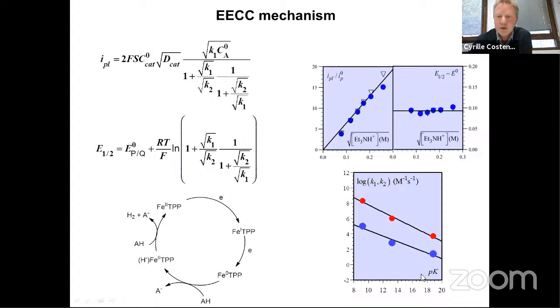And interestingly, if you change the pKa of the substrate, the acid molecule, you get a correlation between the rate constant and the pKa of the acid, which is not surprising, because in each case, if you make the acid stronger, you get a faster formation of the hydride or a faster generation of hydrogen through a reaction of the acid molecule with the hydride. Interestingly, you can see that K2, so K2 is the formation of hydrogen, is slower than K1. So this means that in the process, you will accumulate hydride in the diffusion reaction layer. And this is an interesting situation.